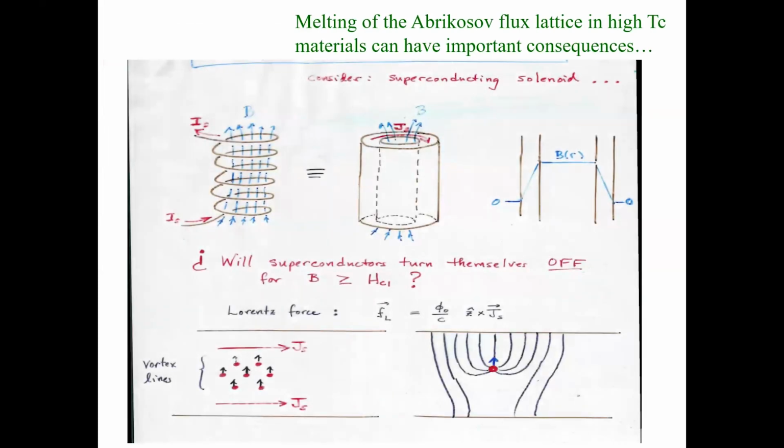It also matters for other reasons. The fact that they have this melting. It's not going to work as a superconductor if, when you apply a magnetic field, the flux lines are free to move. Because, again, I have to ask you to accept this on faith if you don't know it already. What happens, you have a bunch of vortices like this, and that happen to be there because there's a magnetic field. If you now try to run a supercurrent through the material, the vortices move at right angles, and then their cores move and they dissipate energy.